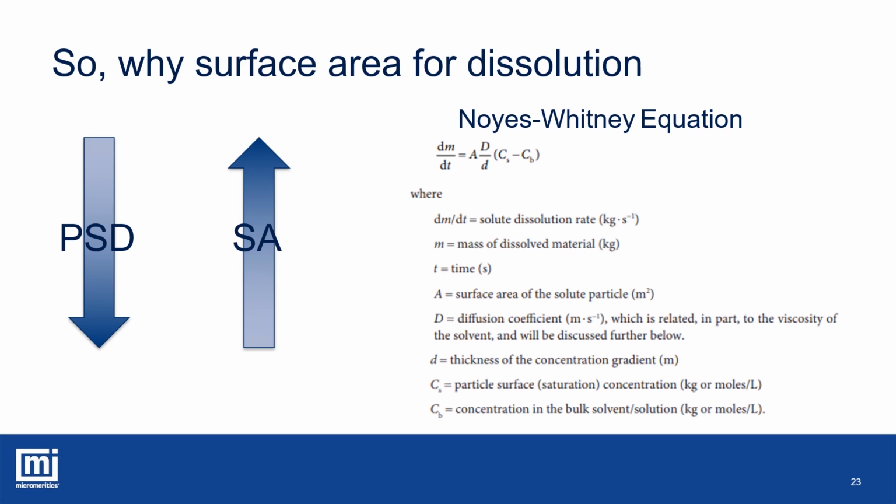So that is why surface area was very important in our lyophilization example, because the dissolution is governed by surface area, not PSD. And also, it was impossible to measure PSD in the intact cake. The vials don't fit in the machine.